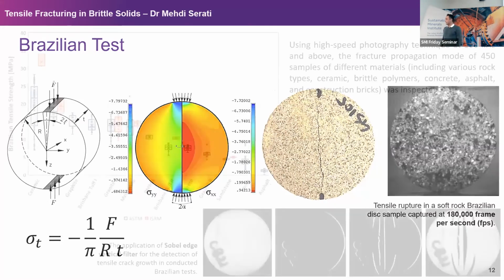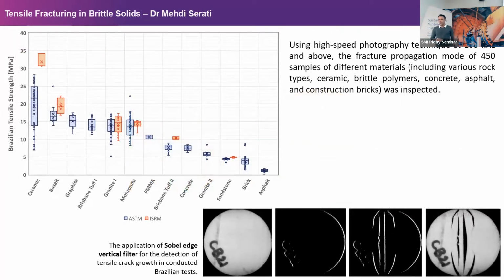and it forms a single tensile crack. In a recent project, we tried to understand what happens if you get a different fracture pattern, a different type of fracture mode, and how it is going to impact our estimation of the tensile strength. That was a maybe 4 or 5 year project. We prepared around 450, I guess near 500, Brazilian samples from a wide range of materials. Here in this chart, you see the distribution of the Brazilian tensile strengths.